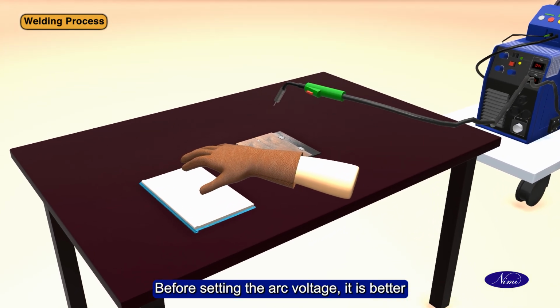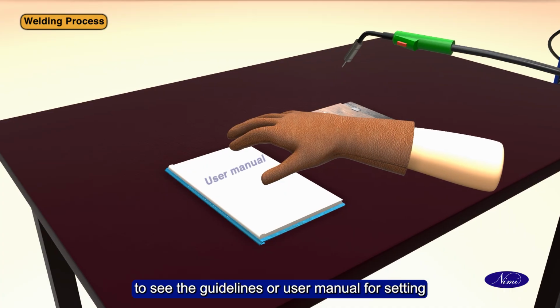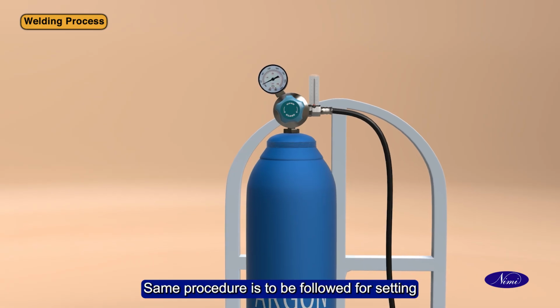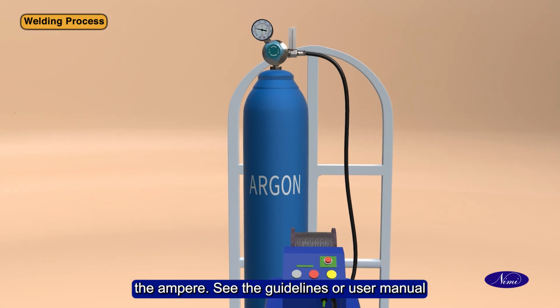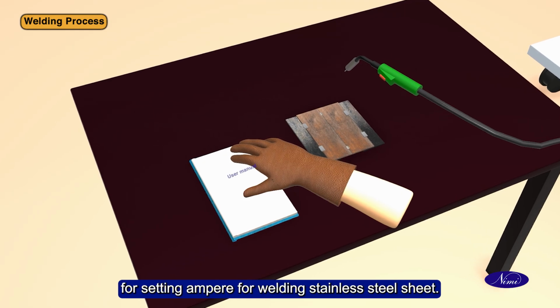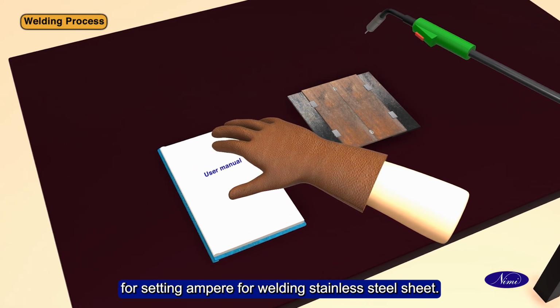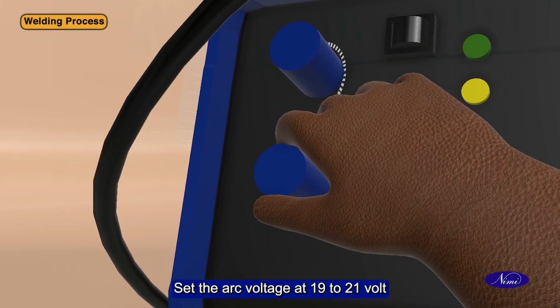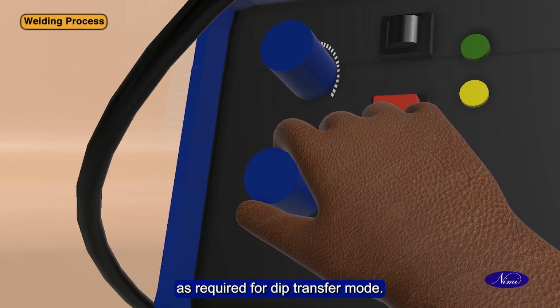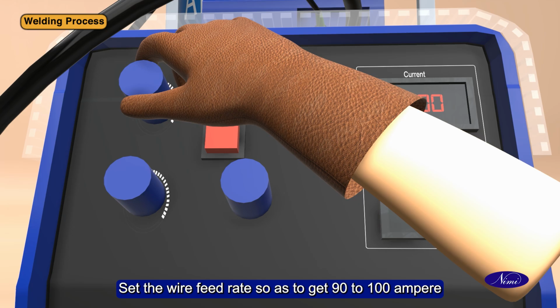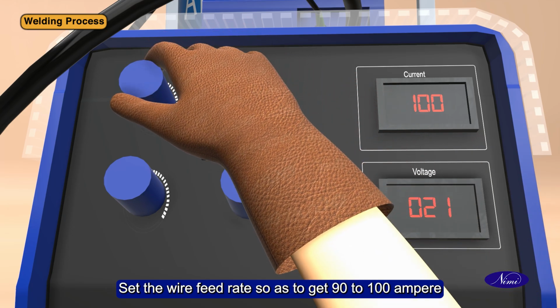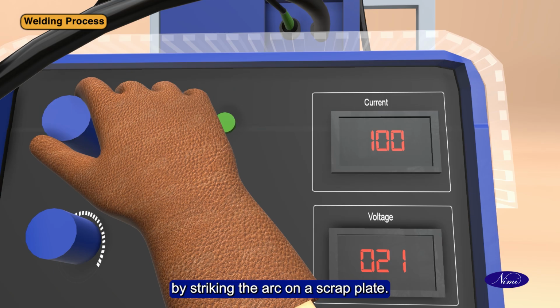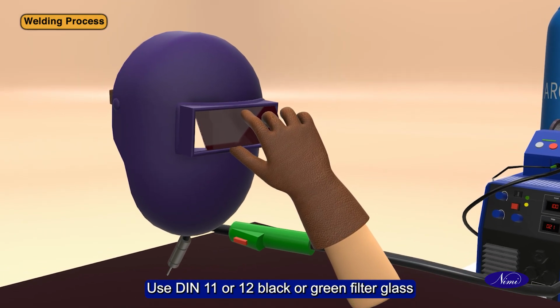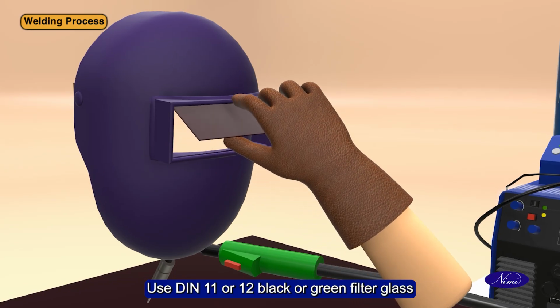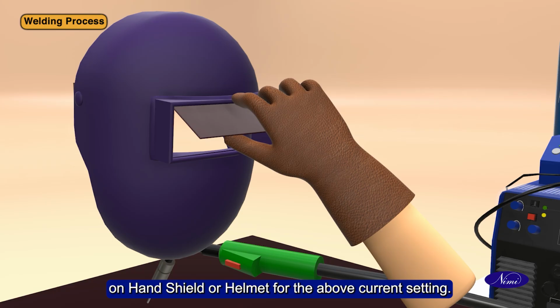Before setting the arc voltage, it is better to see the guidelines or user manual for setting arc voltage for welding stainless steel sheet. Same procedure is to be followed for setting the ampere. See the guidelines or user manual for setting ampere for welding stainless steel sheet. Set the arc voltage at 19 to 21 volt as required for dip transfer mode. Set the wire feed rate so as to get 90 to 100 ampere by striking the arc on a scrap plate. Use DIN 11 or 12 black or green filter glass on hand shield or helmet for the above current